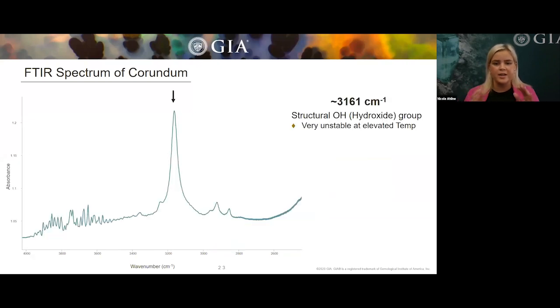An example of that is, again, we zoomed into that area between 2000 and 3800. And what you're seeing right here is a nice sharp 3161 peak. This peak is very unstable at elevated temperatures. So if a stone had this 3161 peak and then it was heated, that peak will actually decrease and be absent from that IR post-heat treatment. So the presence of this 3161 assists the gemologist in a possible no heat call. But if it wasn't there, it just shows that there is no 3161. We can't decipher if it was heated or not heated based off the absence of it in this case, but the presence of it guides the gemologist towards a possible no heat call for this stone.